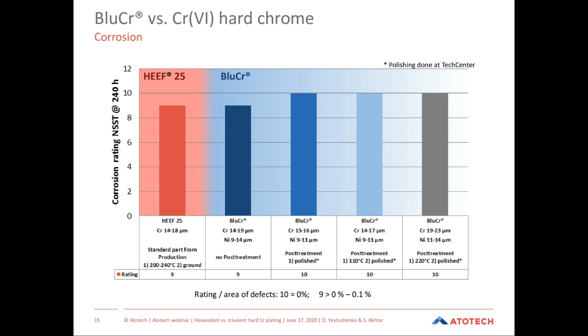But if we look closer at parts which have seen some post-treatment, like heat treatment or polishing, then we can see that corrosion resistance increases for these parts. A very short explanation of why we compare two different temperatures here, 110 degrees C and 220 degrees C. You will see this temperature also later on another slide. This is because it depends on what our end customer is doing and what will be done with the parts.